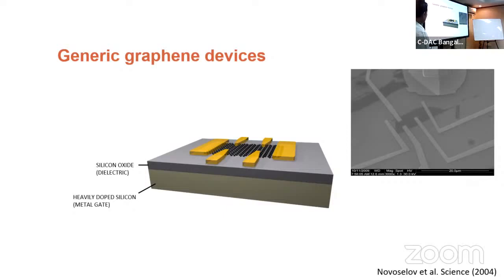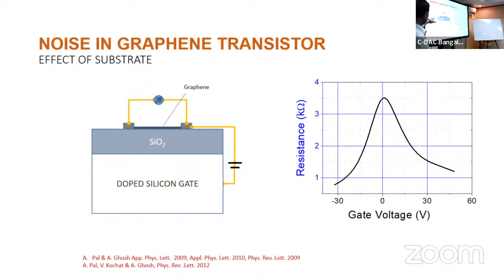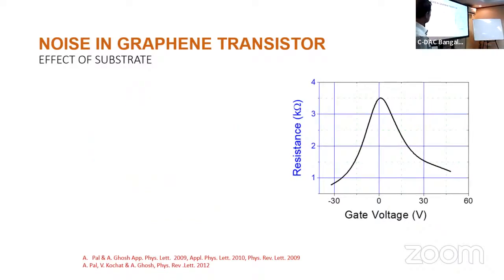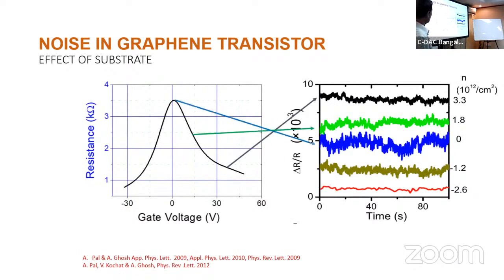So when you measure the electronics of these kinds of devices, you can see that the silicon oxide acts as a gate, and if I apply a positive voltage, the electrons are induced. If you apply a negative voltage, holes are induced. So the resistance comes down on both sides. Typically when we measure noise in these, we measure noise at specific points in the resistance versus gate voltage curve. You can see that when the resistance is maximum, which is at zero electron density, the noise is maximum as well. But if you induce holes or electrons in the graphene channel, then the noise decreases. Okay. So this is something which has been known for a long time. We have been working on this.